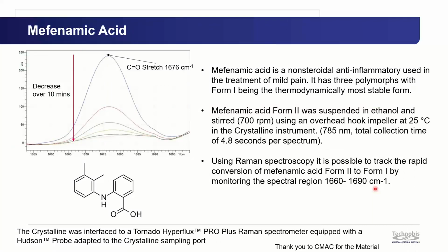So being able to detect form changes as well is very important. In this case, we have mefenamic acid, which is a non-steroidal anti-inflammatory used in treatment of mild pain. It has 3 polymorphs, with form 1 being the most stable. Form 2 is really difficult to obtain. It was really difficult to even prove it exists because it converts so rapidly over time.